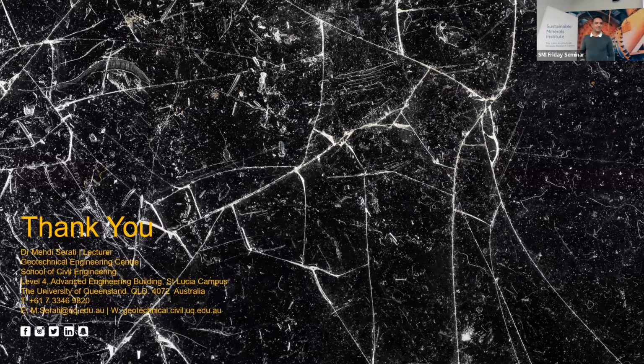Thank you, Mehdi, for a great presentation. I really enjoyed it. You mentioned that the location where the first crack appears is very important to estimate the tensile strength. And you said that when, instead of a full cylinder, you used a half cylinder and adjusted the sample holder, you increased the chance of that first crack coming in the center. You mentioned that it's important to have the sample holder adjusted for the sample. If you adjust the sample holder for the whole cylinder, would that improve the chance of having that first crack start from the center or not?